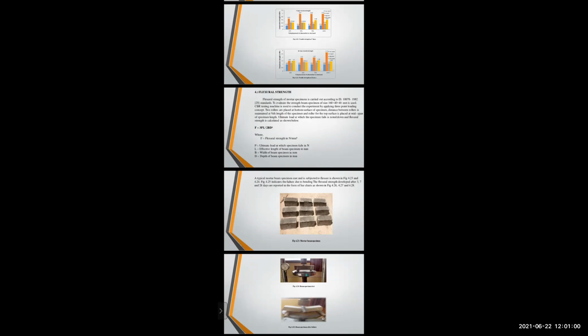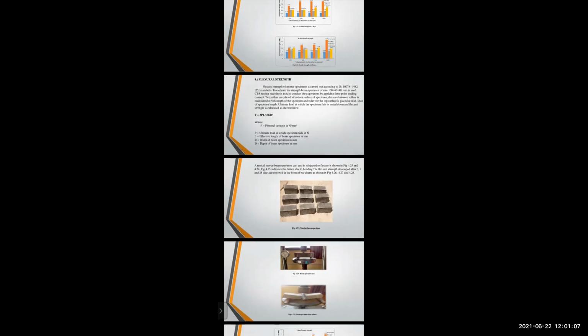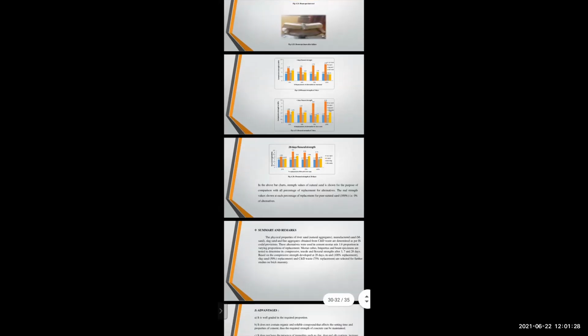The specimen size is 160 by 40 by 40 mm. Using a CBR testing machine, we apply the three-point load concept. We take two rollers at the bottom surface of the specimen, with a distance between them of three-fourths of the length of the specimen. Then the roller for the top surface is placed at mid span of the specimen length. The ultimate load at which the specimen fails is noted down. Then flexural strength is calculated, and the formula is F equals 3PL divided by 2BD squared.